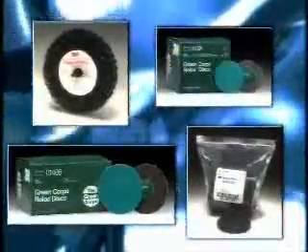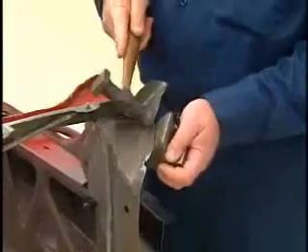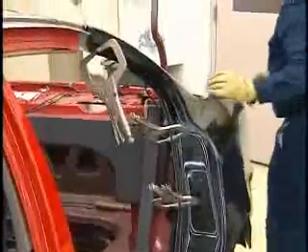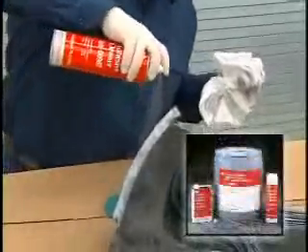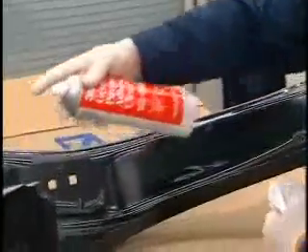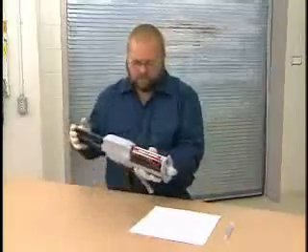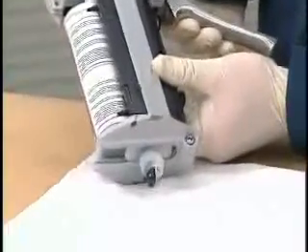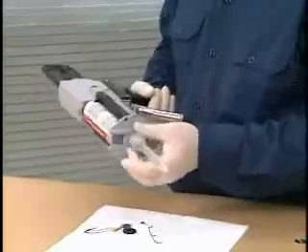Here's how it works. First, remove all paint from the surfaces to be bonded using either a 3M Scotch-Brite Clean and Strip Disc or a Grade 50 3M Green Corps Roloc Disc. Straighten all metal pieces as necessary. Then clamp or screw the part in place and check for proper fit and alignment. Remove the part from the vehicle and clean all the areas to be bonded with 3M General Purpose Adhesive Cleaner or 3M Prep Solvent 70. Place the 3M AutoMix Panel Bonding Adhesive cartridge in the applicator gun. Dispense just enough of the adhesive so you can be sure that parts A and B are present. Attach the mixing nozzle to the adhesive cartridge and you're ready to begin.